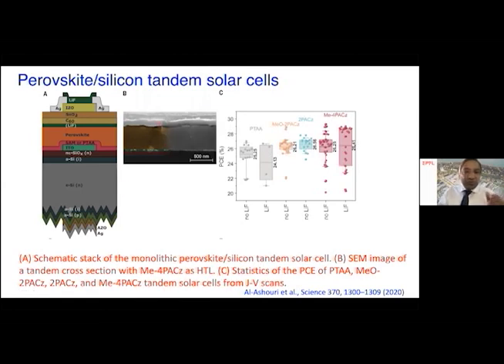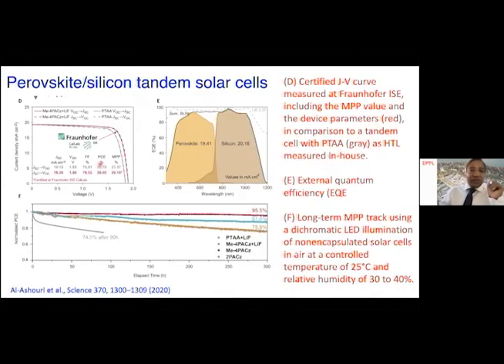Here in between, we have a cross-sectional image of this tandem configuration. Now if you look at the power conversion efficiency, this group has reported 29.1% efficiency. For a similar type of silicon perovskite solar cell, the Oxford group has reported 29.5. So it's in the range of 29% efficiency. Now, if you look at the IPCE measurements of these two cells, the perovskite solar cell on top is generating close to 20 milliamps short circuit current. And the bottom cell, which is a silicon solar cell, absorbs from 800 to close to 1,200 nanometers and generates almost equal current.